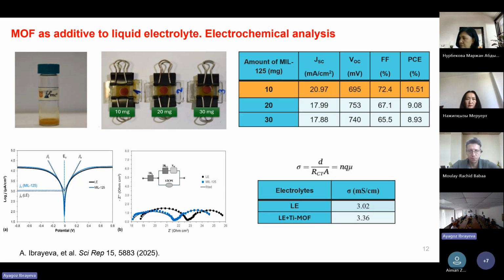Here you can see how it looks in our laboratory. We prepare quasi-solid electrolyte in vials under dark and by continuously stirring. And here is how solar cells looked. In the table, we also provided optimization work to find the best amount of this MOF material, and it was 10 milligrams.